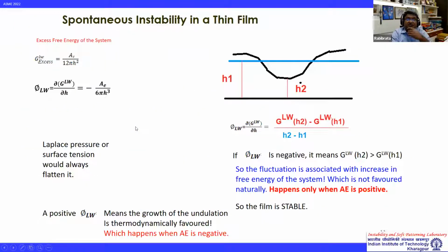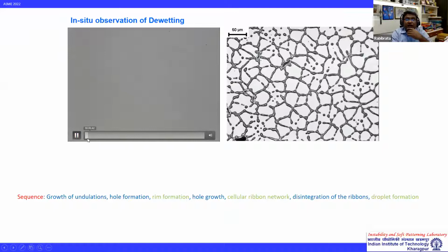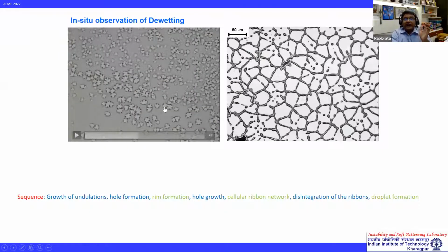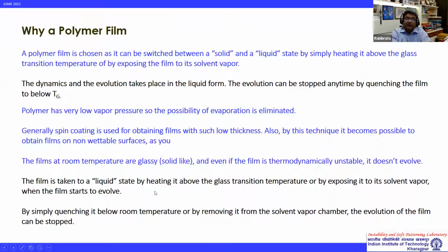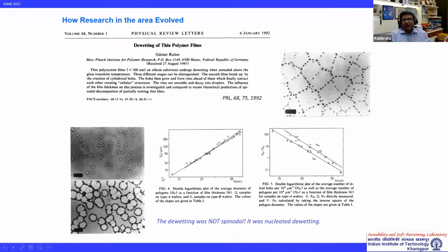And another thing is, just the way when I was playing this video, I can pause it anywhere. You can do exactly the same thing with these polymers. Because if you are heating it above the glass transition temperature, you need not wait for the complete evolution to happen. You can just take it out of the heating, do a quenching to room temperature, or take it out of the solvent vapor chamber, and the evolution will stop, right? So this is the area of spontaneous instability or hydrodynamic instability in ultra-thin films. Why the word hydrodynamic? Because this evolution requires a liquid, or takes place in a liquid thin film.